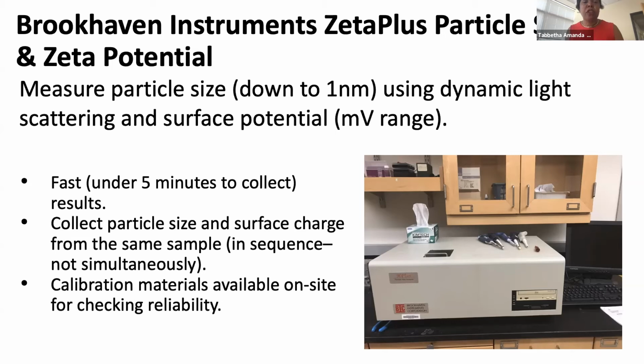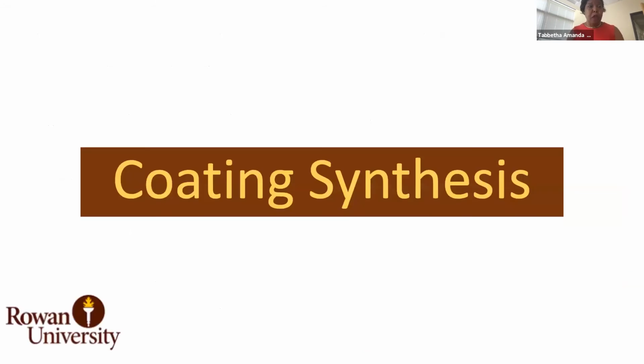potential analyzer. So with this instrument, you're able to determine the particle size of your particular sample in a fluid solution. It is based on the Brownian motion of the particles in the solution. But we're also able to apply a bias and actually drive your particles from one potential region, low potential, to high potential, or vice versa. And based on the rate of motion, if we know the size, viscosity, and things like that, we're able to determine the surface charge on those particles. And this is used primarily for particles as well as proteins.